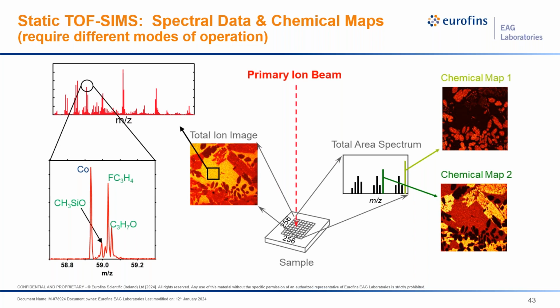Like an SEM image or the SXI image, we have a total ion image. So this is just a total secondary ion intensity coming from the surface. From that image, we can then pull spectral data from wherever we want on that sample. Likewise, we have the collective area spectrum over here, the mass spectrum. From that mass spectrum, we can select peaks, groups of peaks, individual peaks, and create maps. So there's a plethora of information within one acquisition in time-of-flight SIMS.